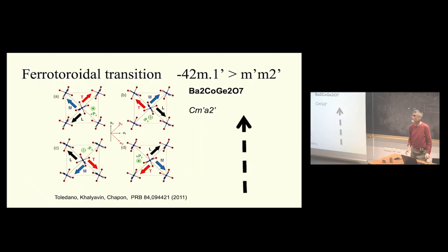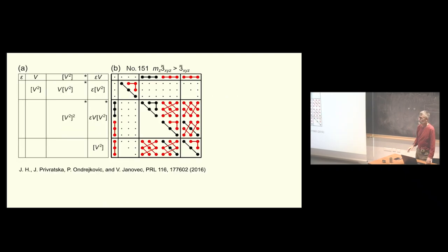So those red dots there are the tensor components that are acquired through the phase transition. For example, this stands for the elastic tensor, and you see that C11, C22, and C33 are allowed, and then C44 is allowed. These were not allowed in the high temperature phase, but below the phase transition, they are allowed. And what is good also is that they are in the same reference frame. So this matrix is already transferred.